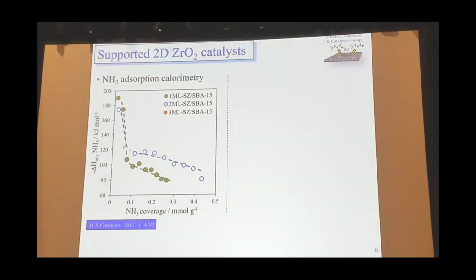What is interesting though, when we look at these samples by ammonia calorimetry, is that depending on how many layers you've got, you actually have some quite unique acidic properties. So the green dots are the ammonia calorimetry for the heat adsorption of ammonia as a function of coverage from layers. a 2-layer and then a 3-layer.